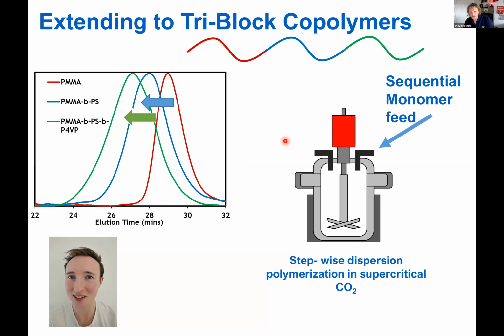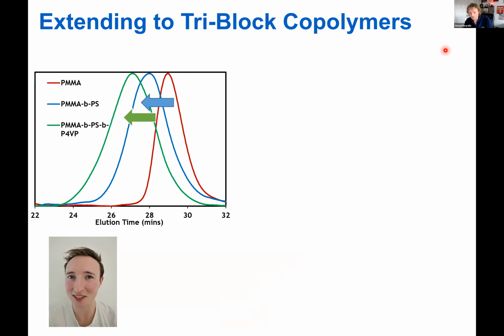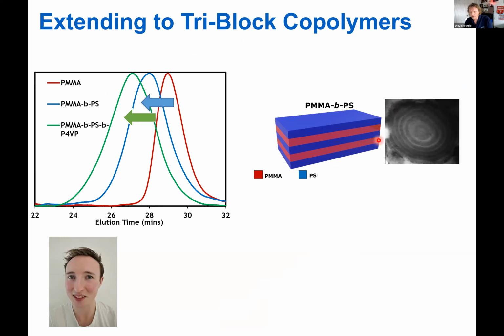Okay, so what Ryan has been doing now in his PhD, he's been extending this, and we're now working with tri-block materials. We've taken PMMA and then added styrene and then added vinyl pyridine to create a tri-block material. We've followed this process, and Ryan has shown that when you have the di-block material, it's a lamellar separation.